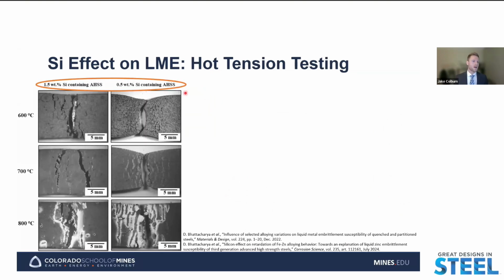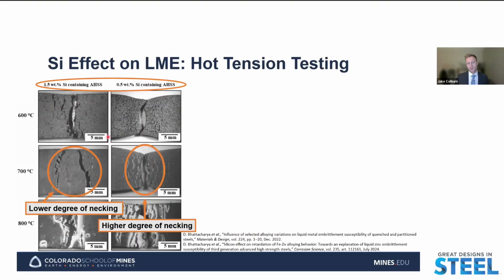As we take a look at some of the results for the silicon effect on LME with our hot tension test results, here on the left we have macrofractographs of the hot tension samples tested at three temperatures: 600, 700, and 800 degrees Celsius. We have the high silicon containing steel on the left and the low silicon containing steel on the right. The main thing we can see is a relatively lower degree of necking in the high silicon containing advanced high strength steel, which is indicative of a lower degree of ductility during testing.